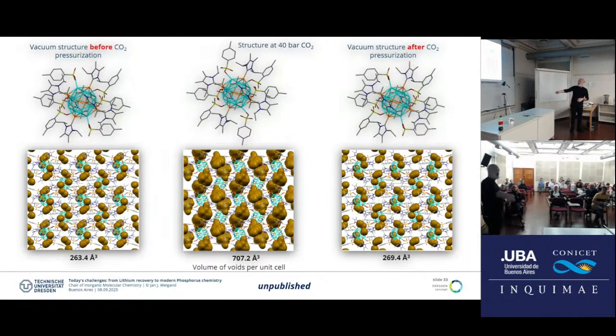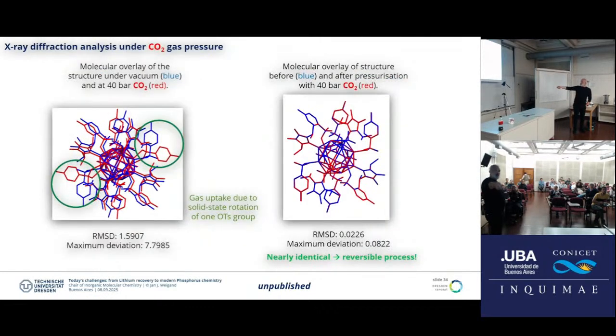And then what we can do, we can take the CO2 out again and then the tosylate goes back. So we have some kind of a pressure-induced gating system in the solid state. And it is reversible. So we put the structure back and forth, and we always come to exactly the same result on the diffractometer on a single crystal. So you see what happens. It's like a gating system which we find quite interesting. And so you see that the structure before and after, really they match. Yeah? So that really is a solid state transformation, which I find quite interesting.